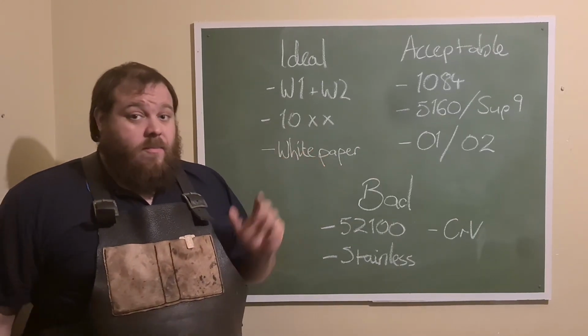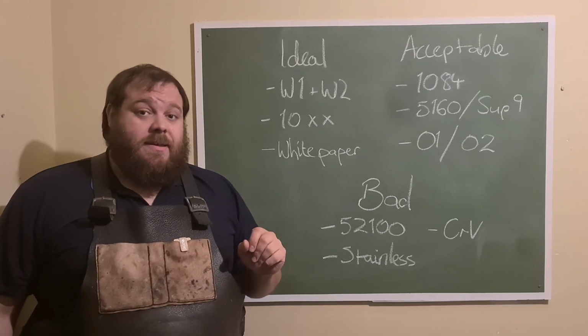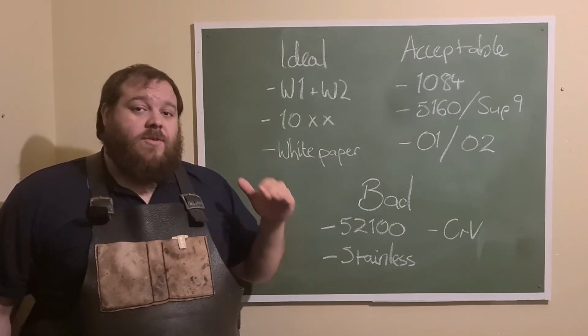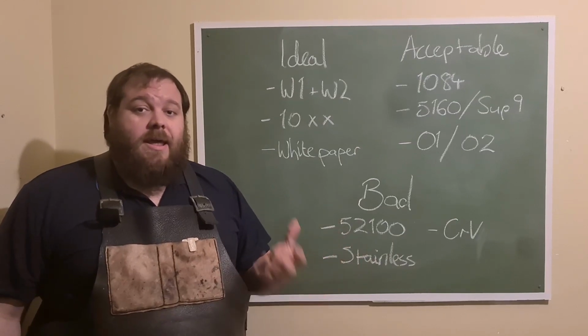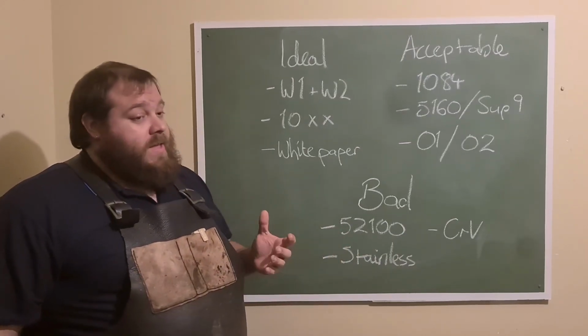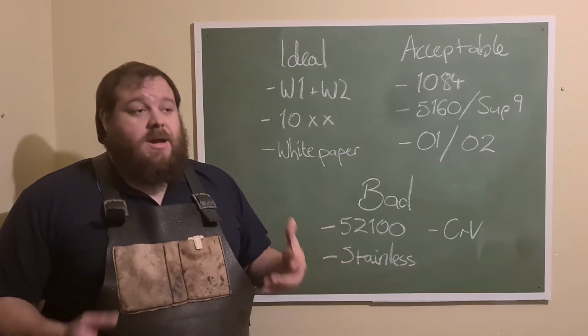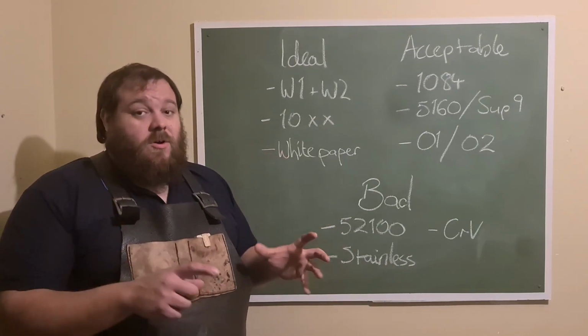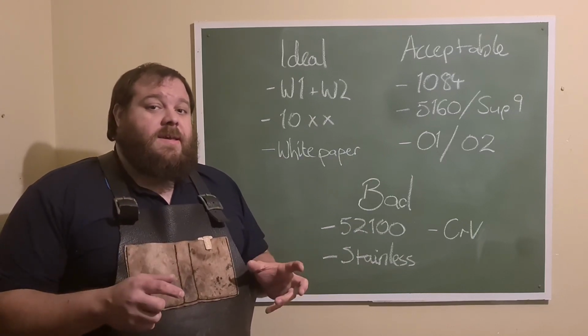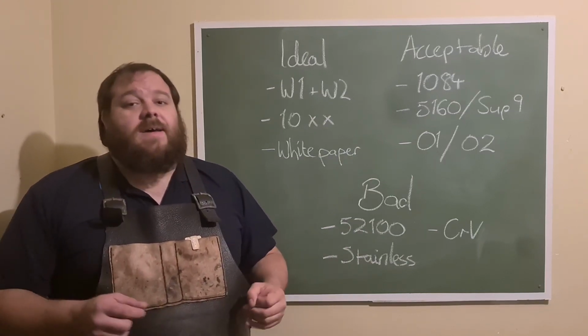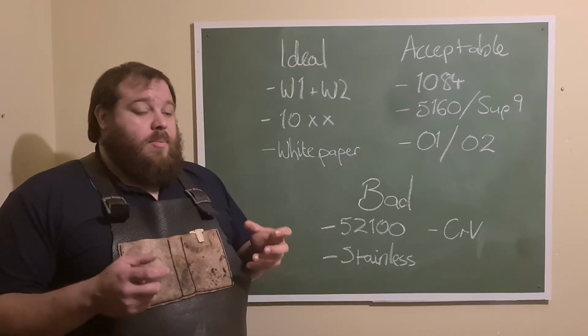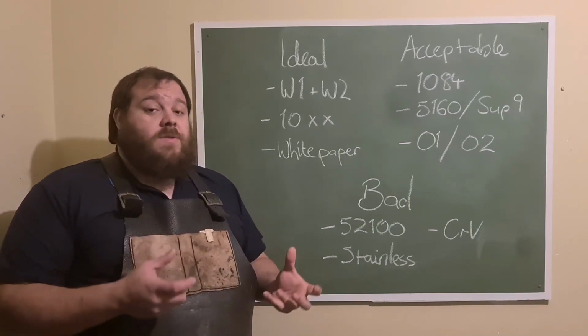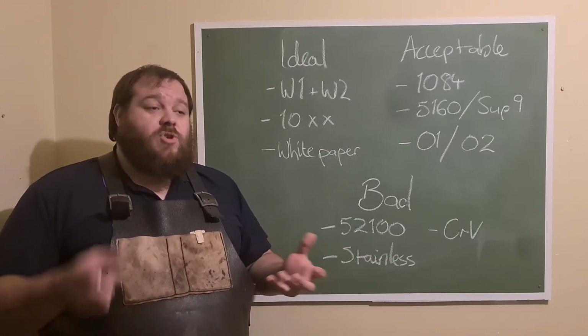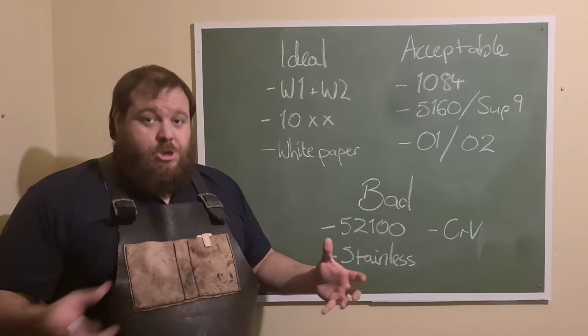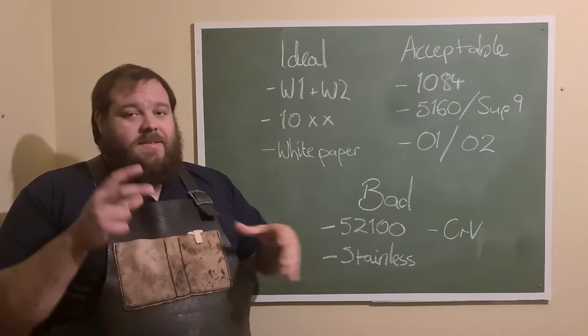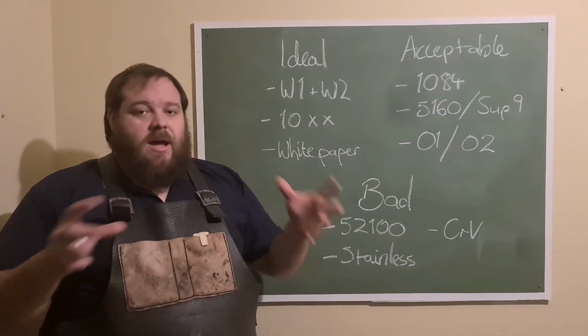The best of them all is 1070 or 1060. Contrary to popular belief, you do not need to be super high carbon in order to get an appreciable Hamon. In most cases, katana and wakizashi and tanto of the Japanese historical tradition are around 0.6 to 0.7% carbon by the time that they are made into blades. When they are brought out as raw tamahagane, they are normally around 1.2 to 1.4% carbon, and then during the folding process, one of the things that they do is homogenize the carbon mixture throughout, because obviously it's patches of carbon steel amongst other things.